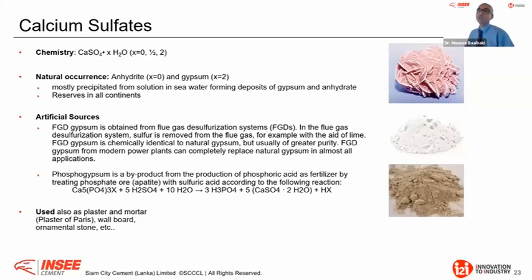Therefore, very often we also see some artificial sources, what we call FGD gypsum, obtained by a flue gas desulfurization system. In flue gas desulfurization, the sulfur is removed from the flue gas, for example, with the help of lime, and the chemistry of this FGD gypsum is very identical to natural gypsum, but usually with even greater purity. Therefore, FGD gypsum from a modern power plant can completely replace natural gypsum in almost all applications.